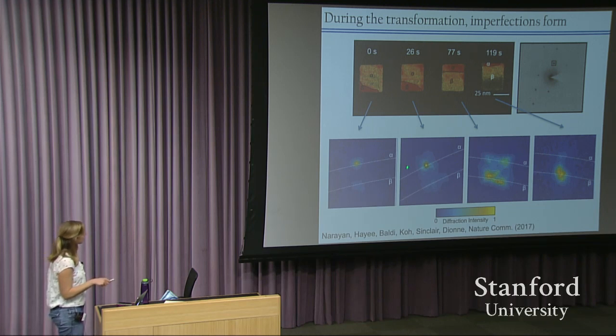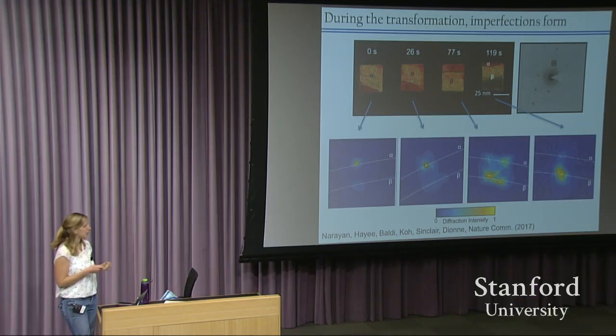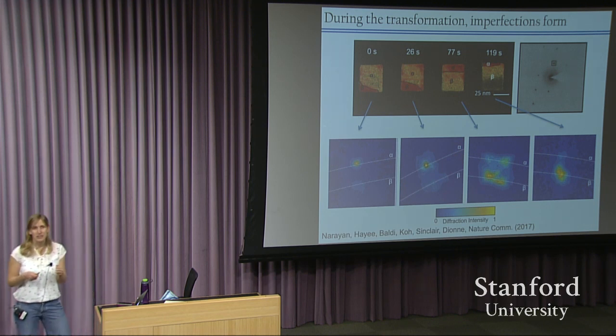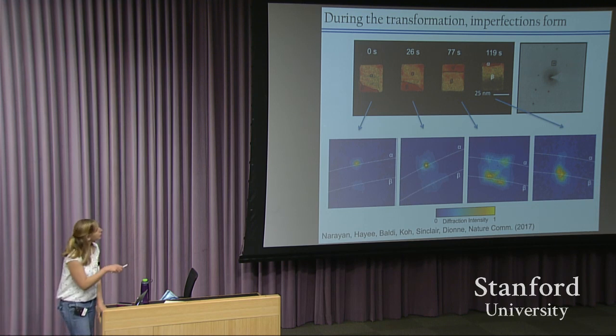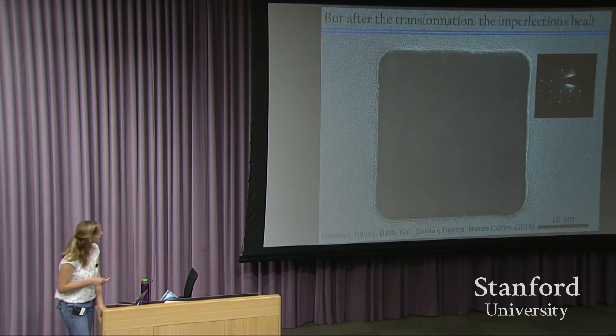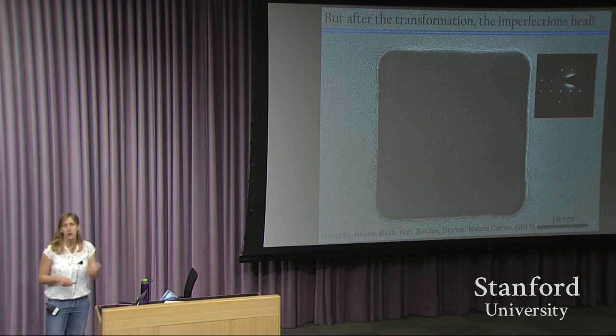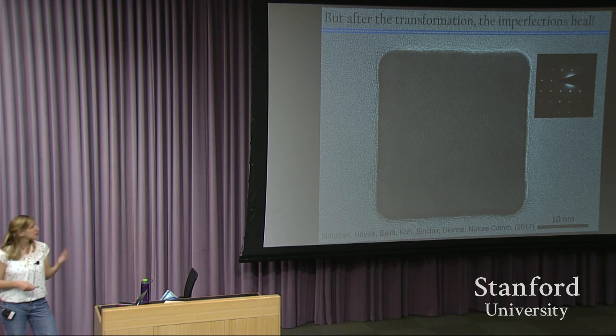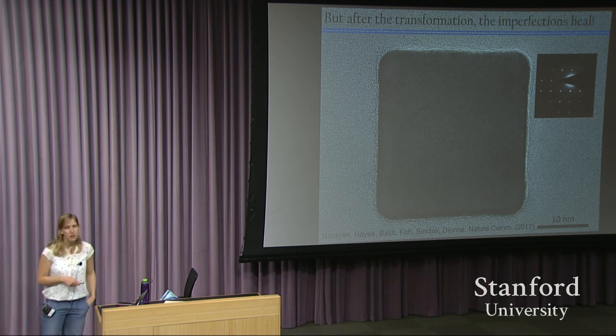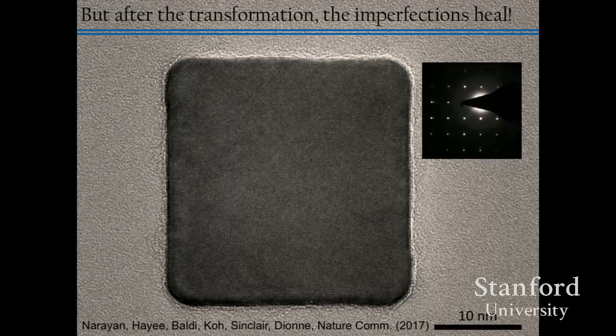But as the transformation occurs, you'll notice that the diffraction spots get more diffuse and elliptical, meaning that basically imperfections are formed. There are lattice rotations and potentially defects that are forming. And then at the end of the transformation, you'll notice that the diffraction spots tighten up again, implying that the nanoparticle is trying to heal its imperfections. And if we go back and take a diffraction pattern of the pure beta phase nanoparticle, it's again back to a perfect single crystal. So really importantly, these small single crystalline nanoparticles, even though they exhibit phase coexistence during the transformation, have the ability to heal themselves at the end of the transformation.